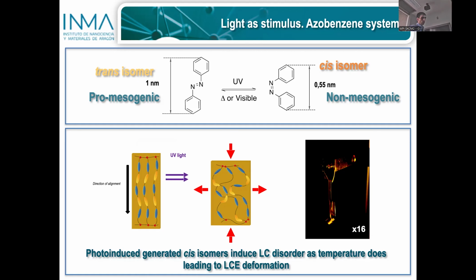But we also like to include in our system this interesting molecule. This azobenzene molecule, in the thermodynamically stable state, has this elongated pro-mesogenic shape, but when you irradiate it with UV light, it isomerizes into this isomer that is not mesogenic. This molecule disturbs the liquid crystal phase, and depending on the substituents we put on these carbons in the molecule, we can make this more or less stable. In the system that we will show you, we have a substituent that makes these molecules very stable in time. It can last for a few hours.